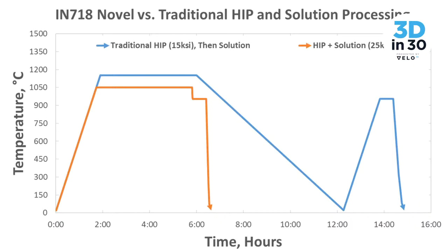Yeah, so this is a simple outline. It's fairly representative of actual heat up and cool down rates, though it's not an actual chart. But what you see is the blue curve shows two peaks, so two different separate thermal cycles. One is common for Inconel 718 that is hipped, where it is isostatically pressed at that high temperature and pressure, and then it's slow cooled. And that is to consolidate the material and eliminate porosity.